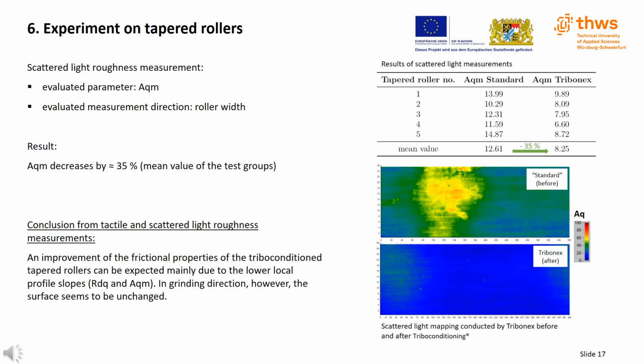For the scattered light measurement, the scattered light parameter AQM was evaluated. This parameter represents the mean value from several measured AQ values. In this case, the evaluated measurement direction is the roller width. The table on the right shows the results for the tapered rollers Standard and Tribonex. The parameter AQM decreases by about 35% due to triboconditioning.